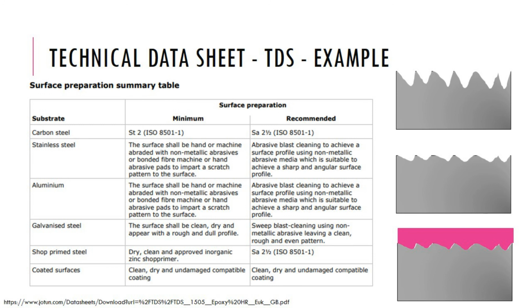The substrate is prepared to a rough profile, which can be either the first one or the second one. The depth of these profiles will decide how adhesive the coating is to the substrate. If the depth is too much, then a lot of coating will be used, and even though the adhesion is more, the cost will increase. If the depth is too less, then the adhesion of the coating will not be enough. Therefore, it is important to select the perfect surface profile and hence go by the recommended standards.